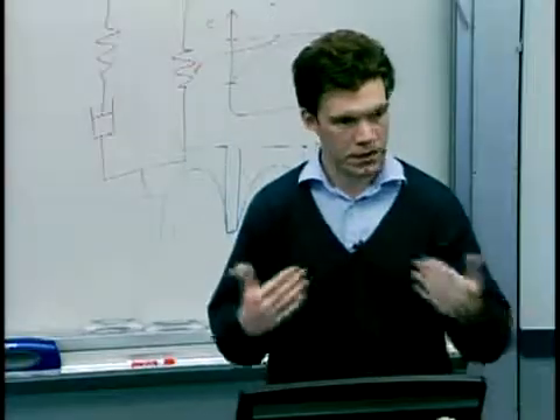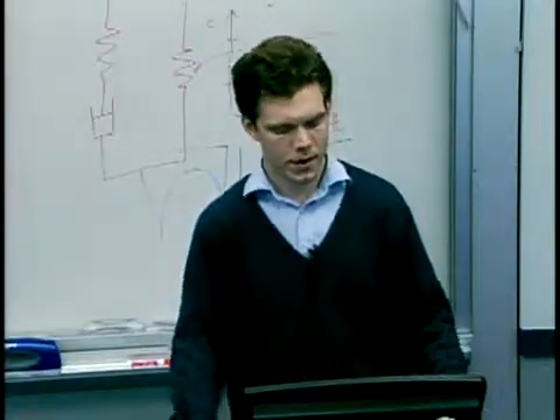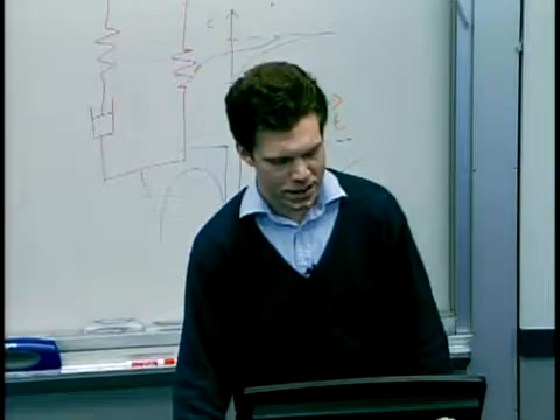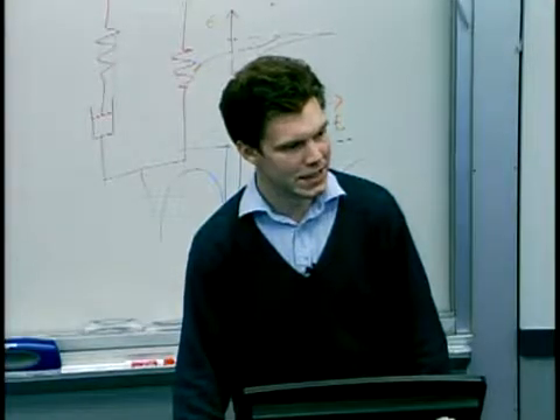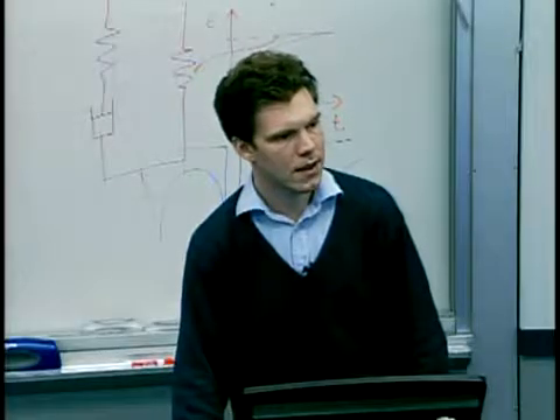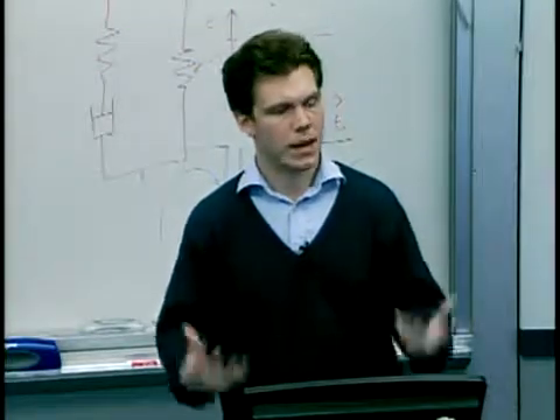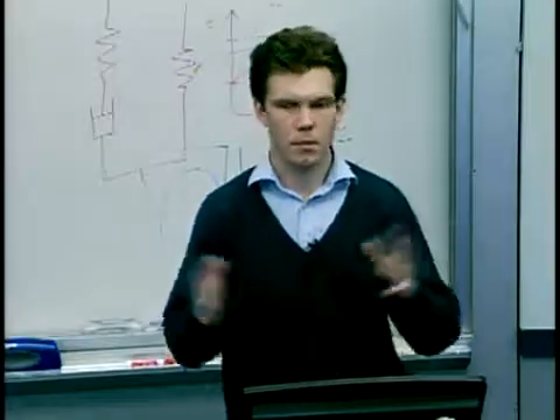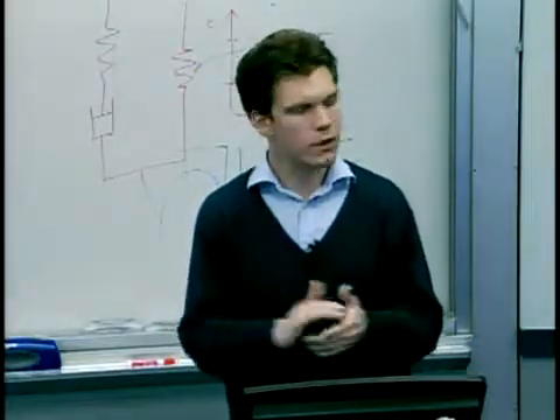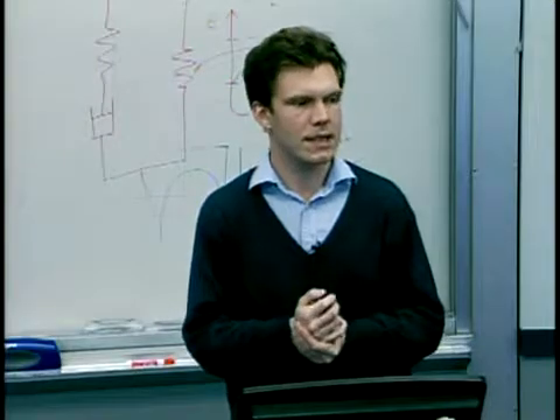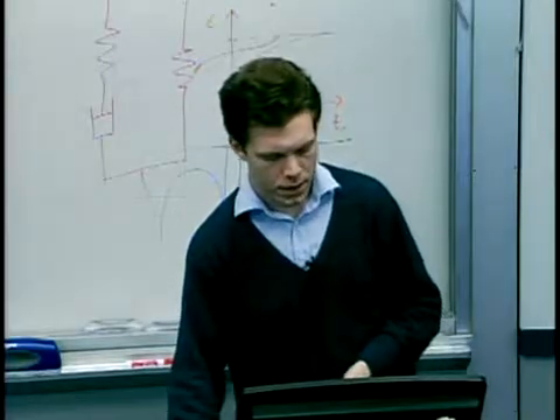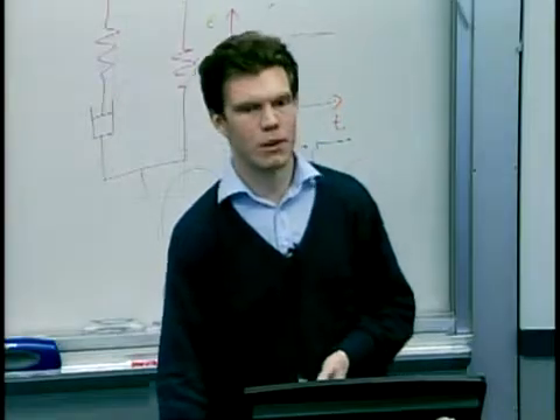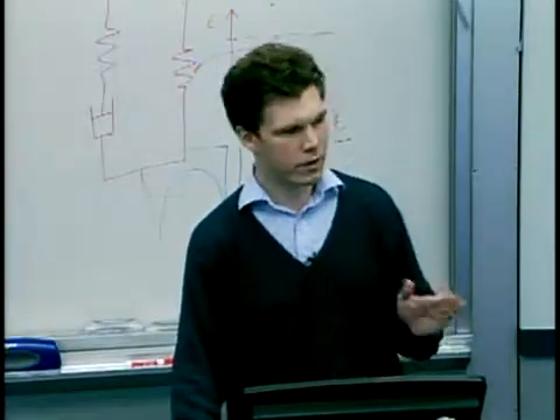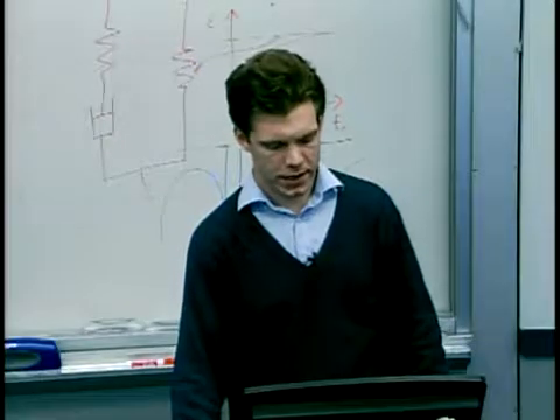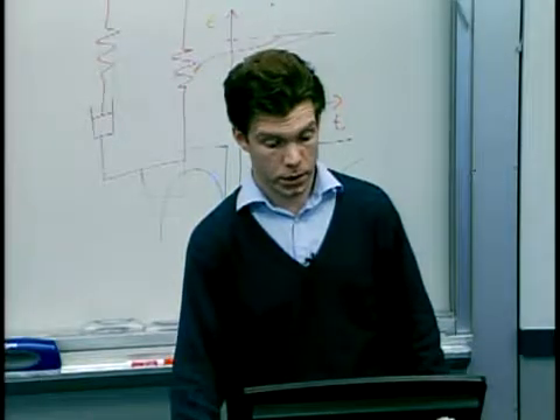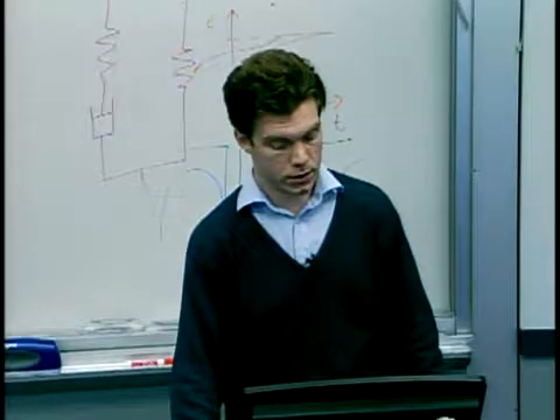And that would be a really logical thing to say. From a process control perspective, however, you can see that this may not be a very good place to operate, where modulus is highly sensitive to temperature. And in our personal experience with lab apparatus, and this is probably different in industry, controlling the temperature is fairly difficult. This is quite an optimistic error bar, in fact, to put on the temperature. So that's, I think, a really relevant consideration for choosing hot embossing parameters, how sensitive we are to temperature.